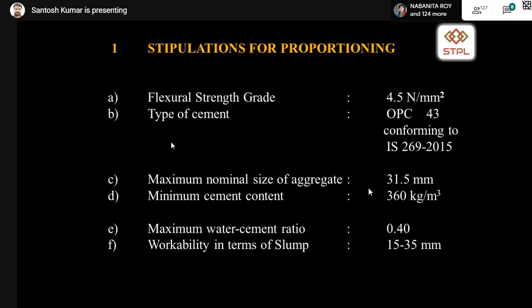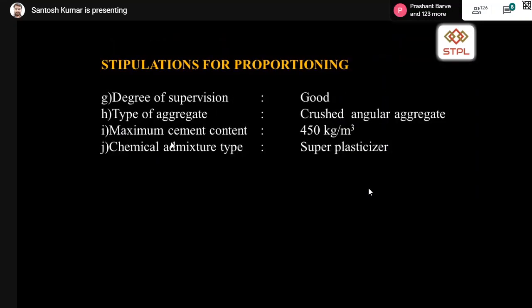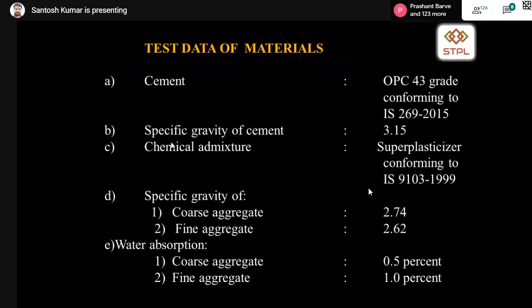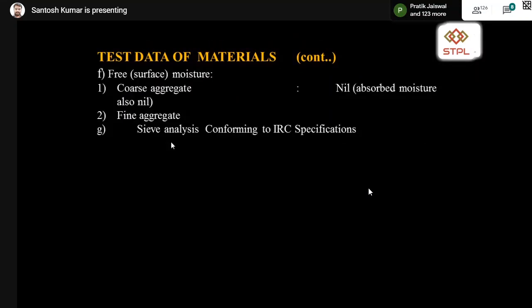Cement considered here is OPC 43. Nominal maximum size in this case taken is 31.5. Minimum cement content is 360. Maximum water cement ratio is 0.4, and slump is again 15 to 35 mm desired. And all other things are same. And if you can see, the specific gravities and the absorption properties are same.